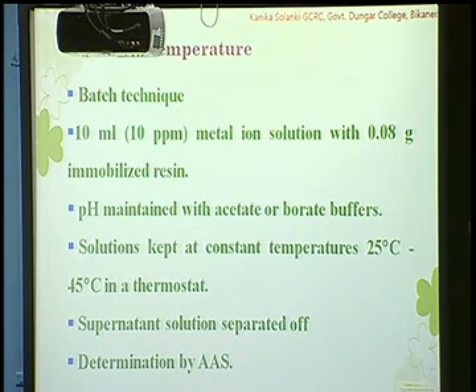Effect of temperature. To investigate the effect of temperature, we have used a batch technique. The solutions were kept at constant temperature between 25 degrees centigrade to 45 degrees centigrade in a thermostat. Supernatant solution was separated off and determined by means of AAS. The adsorption increases up to 35 degrees centigrade, it becomes constant up to 45 degrees centigrade, and then it decreases